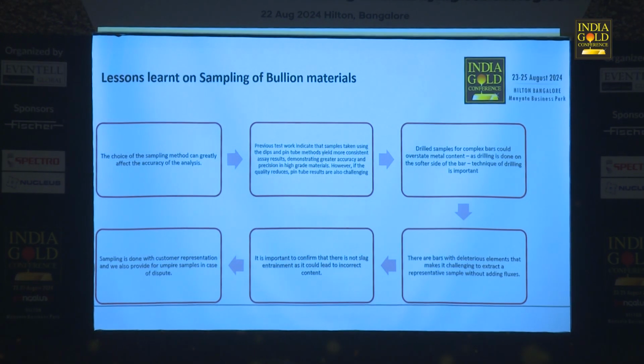So what have we learned about sampling? That the sampling method is very important for the analysis. Number 2, based on the 2019 work, what we have noted is that when the purity starts to be low, especially for the pin tube, it becomes challenging, because you can take a pinch sample, but it will not be strong when you prepare it, according to what my presenter said earlier. So it creates challenges. Pinch are usually good for high purity as well, but for the grades that we've seen in the mining where the gold can become 30%, pinch don't work. Drill samples, from the picture that I showed, if the bars are pure, the drill samples will work. But if you start to have other deleterious elements, people tend to drill from the softer side. The hard side is not drilled, and it gives skewed results. So those are the lessons that we've learned.